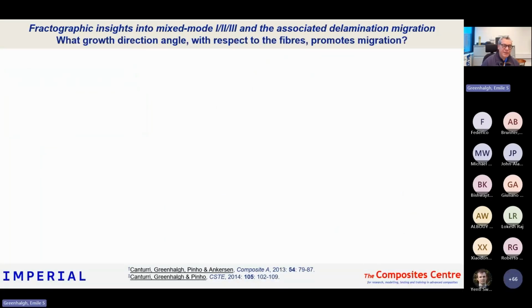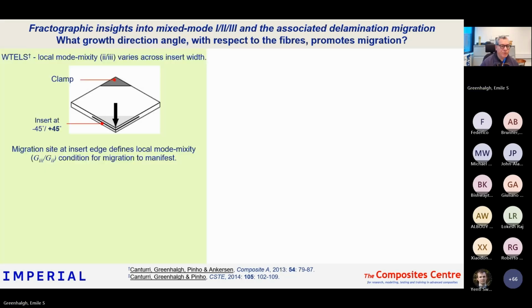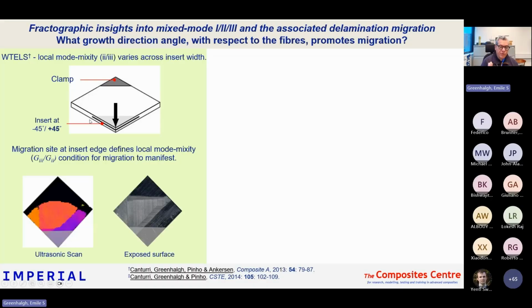So where we try to take this is, what is the growth angle that you can drive a delamination that causes it to migrate? So if it's along the fibers, it doesn't migrate. But if you start to deviate from that, what angle could you get to where it starts to migrate? So we developed a test called the width tapered end loaded split test, whereby we apply a point load to this diamond shaped specimen. And you can imagine as you apply a load here, as you move away from this point, you start to develop a higher mode 3 component. But of course, we defined the mode mixity locally using the expressions that I showed earlier.